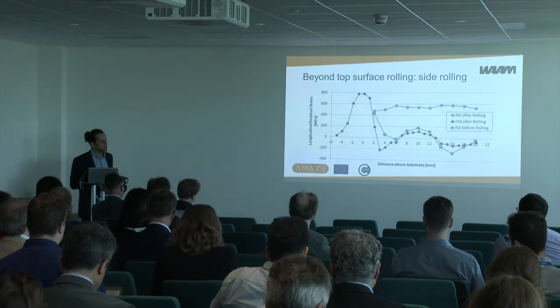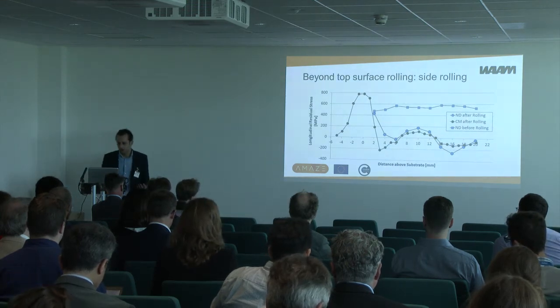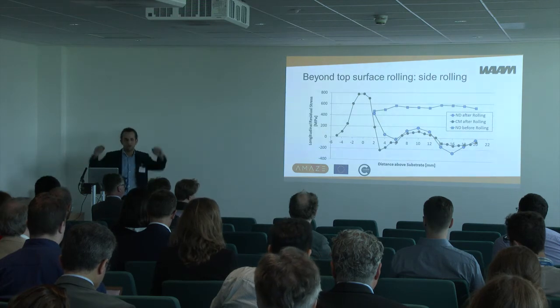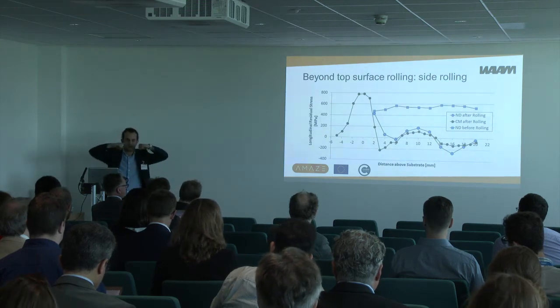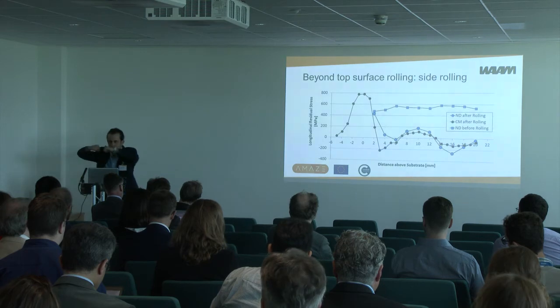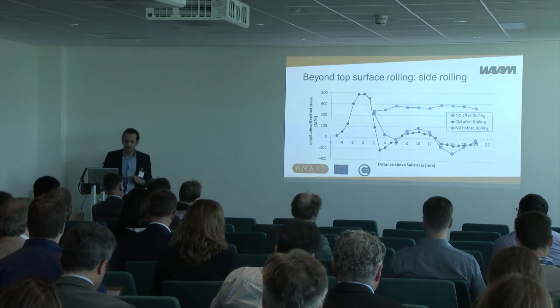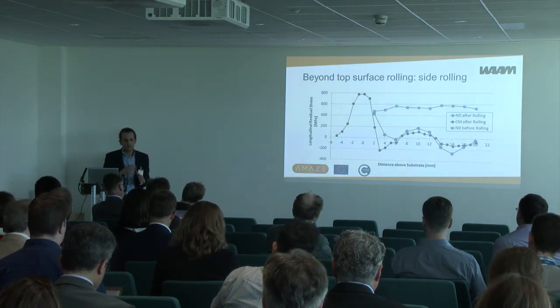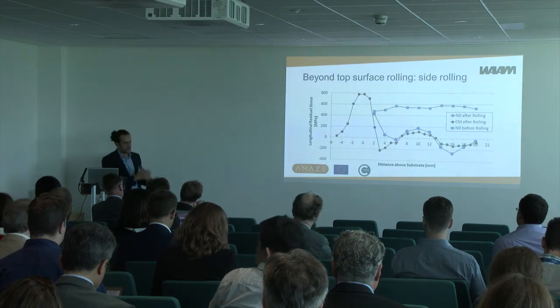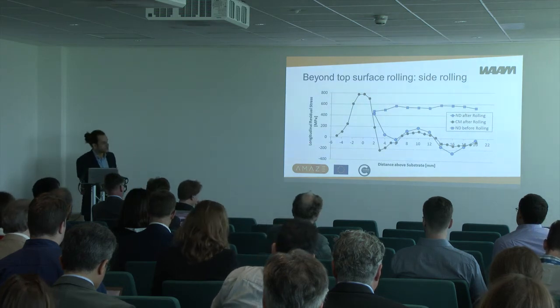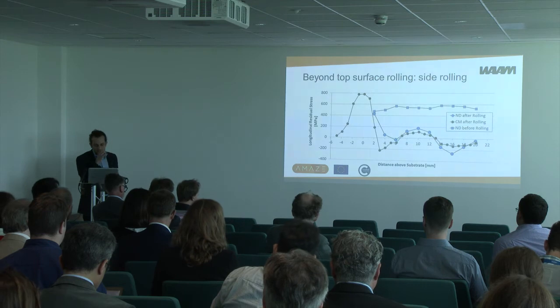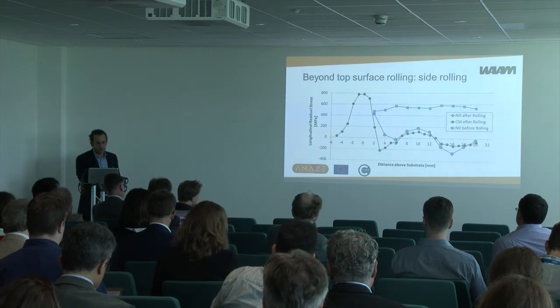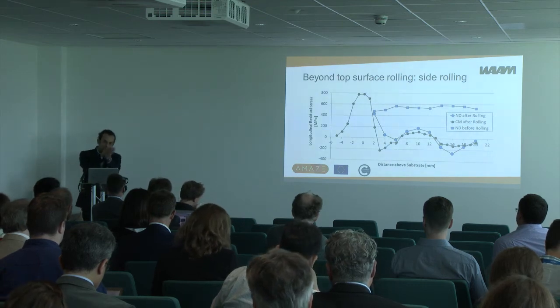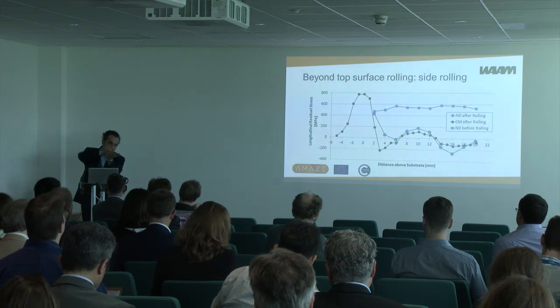Now, the problem of top rolling, as I said, is that it doesn't restrain the material in the transverse direction. So what we thought we would do would be to use something called pinch roller, in which you've got 2 rollers that are going against the parts and are rolling in the direction of the travel rather than from the top. We didn't know how to implement this in practice because we didn't have the time to design the device. So the easiest thing to do to simulate this, or to cheat in a way, was to build a wall and then flip it by 90 degrees and then literally just roll it on the side using a normal roller from the top.